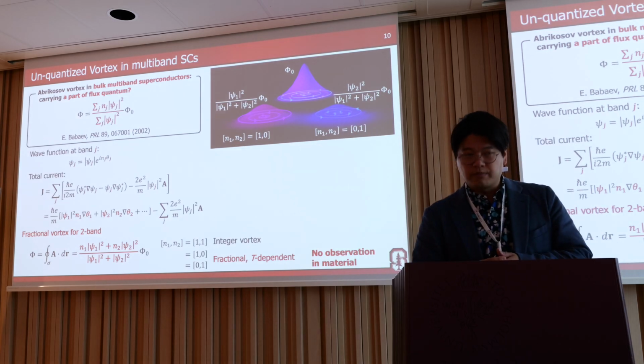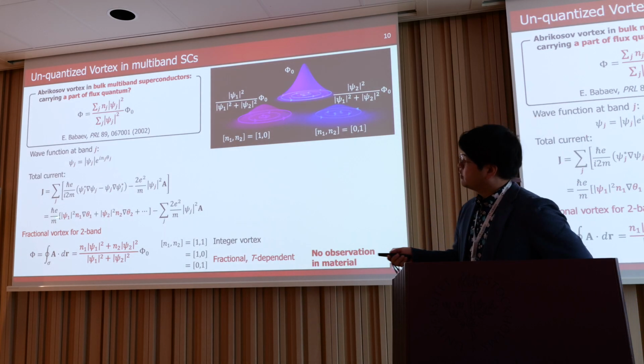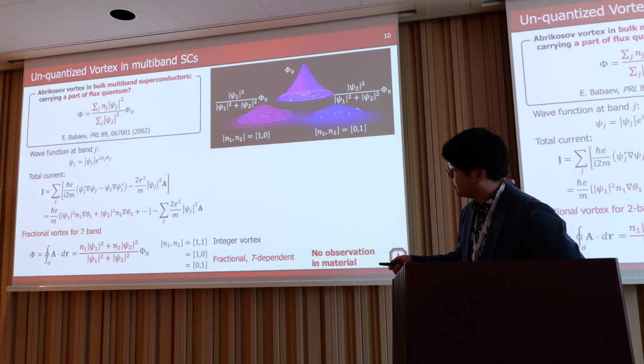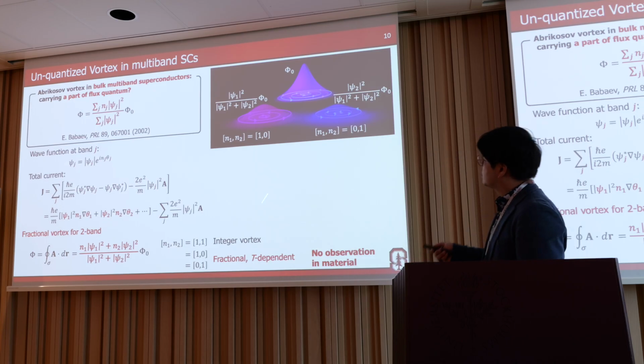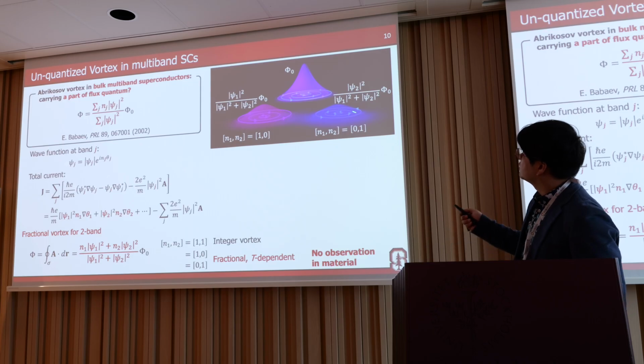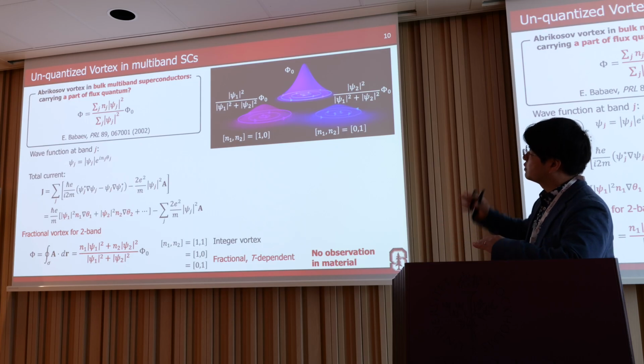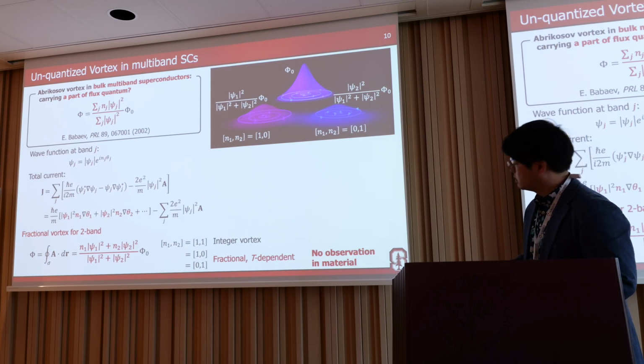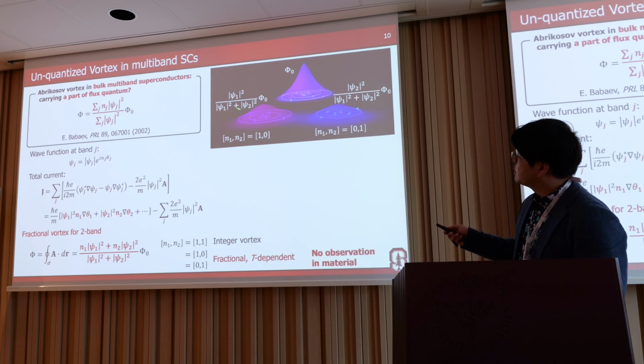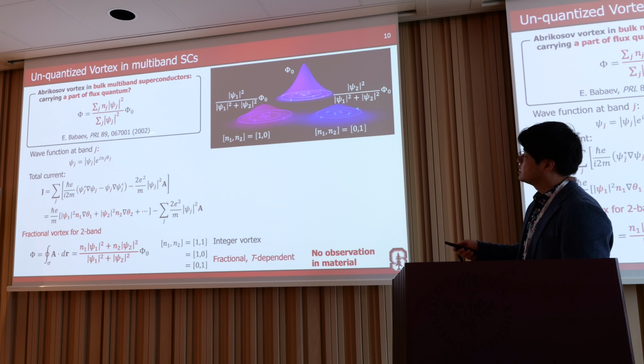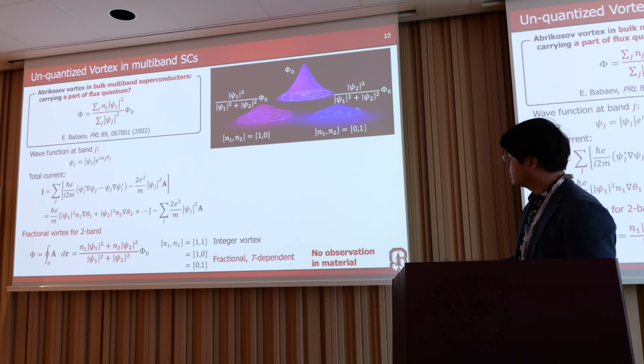For the multiband case, it's more complicated, as Igor said this morning. He calculated the total current for all bands, at the Fermi energy, for a simple two-band model. N1 and N2 are the integer phase windings, but if N1 and N2 are different, the flux becomes a fraction. For example, N1 equals 1 or N2 equals 1. There's a different fractional vortex, but the total flux is still quantized. If psi 1, psi 2, and all the parameters have different temperature dependence, then this value is also temperature dependent. But since 2002, there has been no direct observation in a real material.